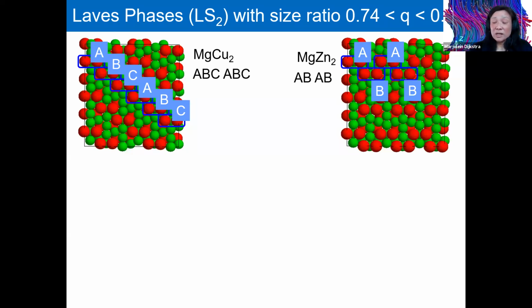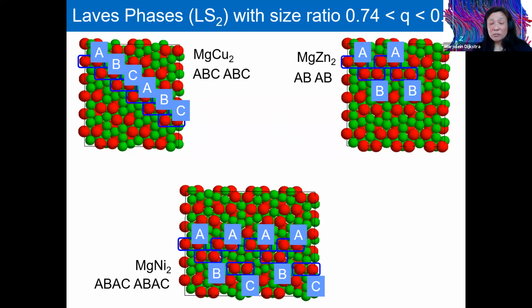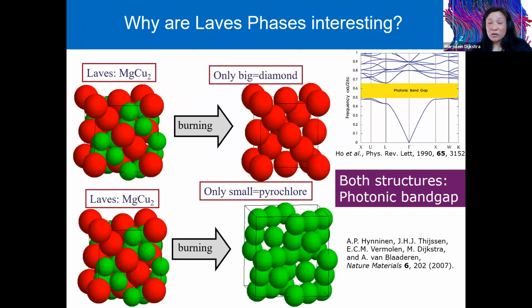Whereas in the magnesium zinc 2 phase, which is the most stable Laves phase, the stacking is AB for the dimer lattice. And then there's a more exotic stacking in the magnesium nickel 2 phase, where the stacking is ABAC, ABAC. And so the most interesting phase is actually the magnesium copper 2 phase, which is actually not the most stable phase, but it consists of a diamond lattice of the big spheres and a pyrochlore lattice of the small spheres.